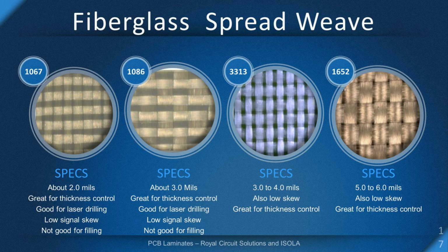What this helps with is that fiber weave effect, which is essentially your timing skew across the panel. So if you can imagine the signal going across this area, it will be much more uniform versus going back to the open weave. Some people might ask, why wouldn't you use a mechanically spread weave all the time? The issue with the mechanically spread weave is you don't get that resin flow to go and fill copper as good as you would get with an open weave. So when you're going with your stack up, that's one of the items you need to think about.